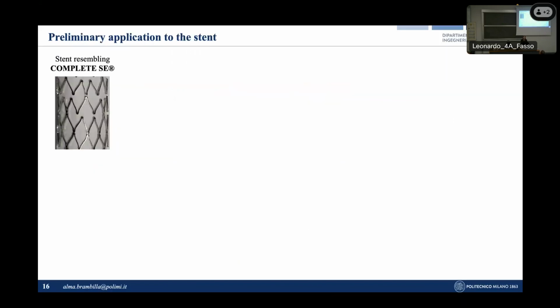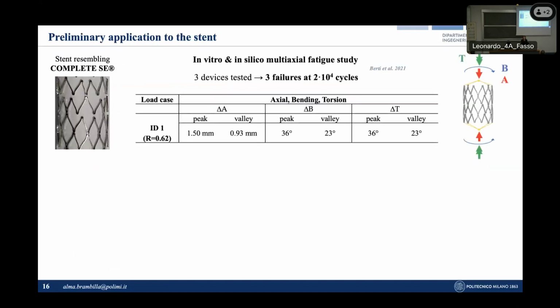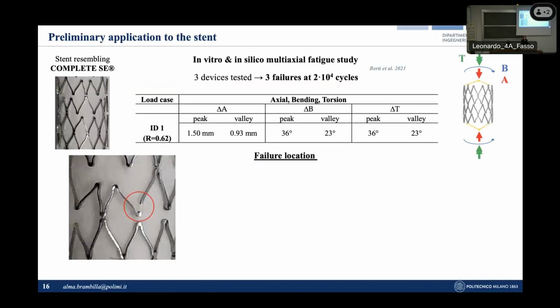Then, starting from these results, we started to investigate the application of this kind of approach to a stent resembling the commercial complete geometry, which was manufactured during our previous PhD thesis. So, to this purpose, the previous fatigue tests were exploited, in which 3 different devices were tested, applying a multi-axial load resembling in vivo conditions, combining axial compression, bending, and torsion. In the test, all the devices failed at about 20,000 cycles, fracturing in correspondence of the peak of the V-shaped structure in all the cases.